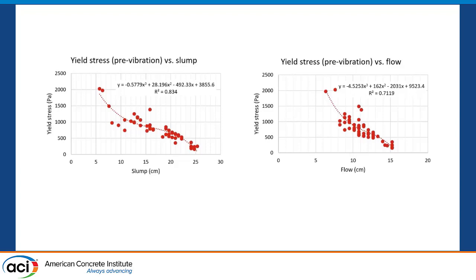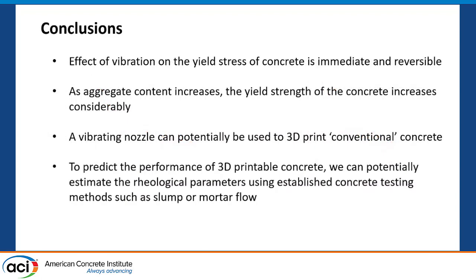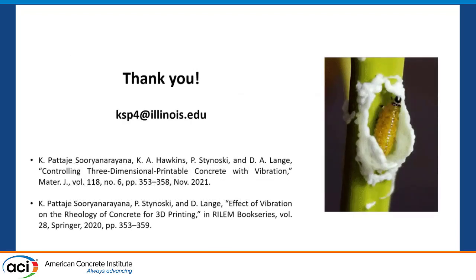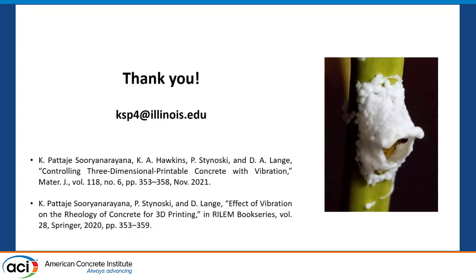So stay tuned for more results. Conclusions: the effect of vibration is immediate and reversible. As aggregate content increases, yield strength increases. Vibration could potentially be used to 3D print conventional concrete. And maybe we can establish regression models for a given lab and given aggregates to predict behavior. Thank you for your time. Humans are not the only ones who 3D print — nature has its own way of 3D printing. Maybe we can learn something from out there. Thank you.